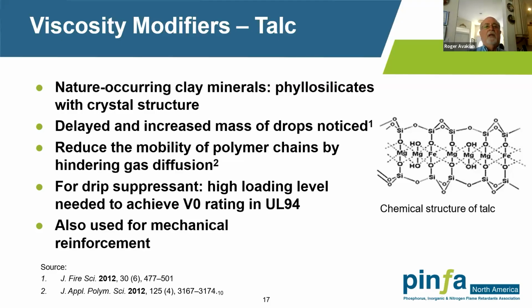So you need to talk with the suppliers, saying that you're interested in using talc as a drip suppressant. As most people know, talc is also used as a major reinforcement in polymers like polypropylene, for instance. What this platelet material does is reduce the mobility of the polymer chains, as well as reduce the mobility of gaseous materials coming out, hindering gas diffusion. Unfortunately, typically you need to use fairly high levels to achieve the V0 rating in the UL94 test, much higher than, let's say, 0.5%, in the literature and by my experience as well. The other key thing is that talc more recently has had some scrutiny with regard to how much silica content is in the material. So there's been some looking at that material as well, something to be aware of. Next slide.